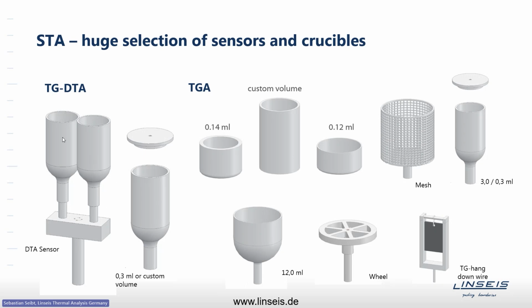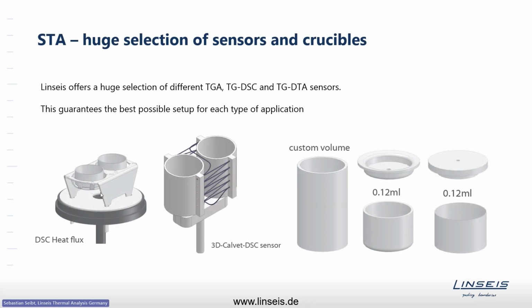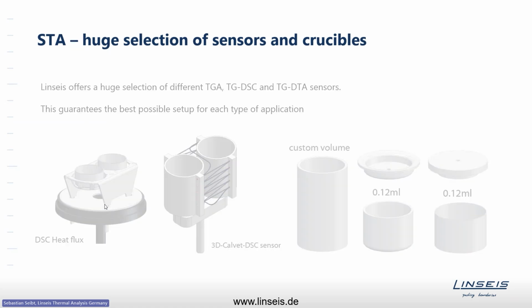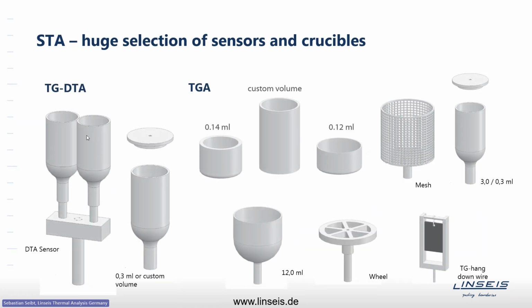However, the TG-DTA has the advantage that you can also measure bigger sample volumes of 0.3 milliliters, and you can measure in more corrosive atmospheres, or measure corrosive samples, as your sample holder does not show any open bare wire or thermocouple that could be corroded. While the DSC sensor with its naked metal surface sometimes tends to react or be corroded, the drawback of the DTA is that it does not provide a quantitative analysis, but a qualitative analysis of the heat flow, and there's no risk of breaking the sensor. So we have the DTA sensor, and we have the pure TG setup.